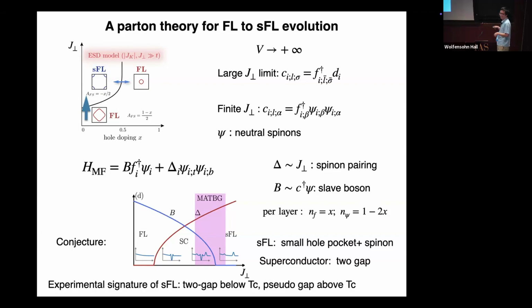Then the transition, if you want a direct transition, you need fine tuning. So my guess is there is always an intermediate regime. Both order parameters are not zero, and this is the superconductivity. So you can check that. So this superconductivity has two sides, from large Fermi surface or small Fermi surface. Of course, at zero temperature, it's just a crossover. But you can still ask, what is the experimental signature of this superconductivity on these two sides? It turned out you can see it from STM.